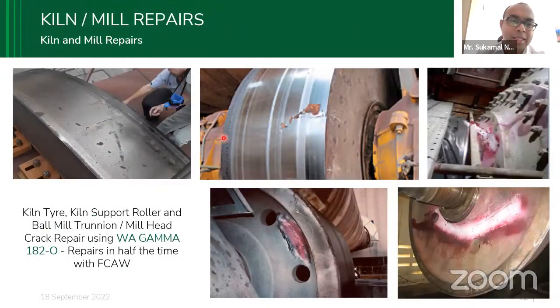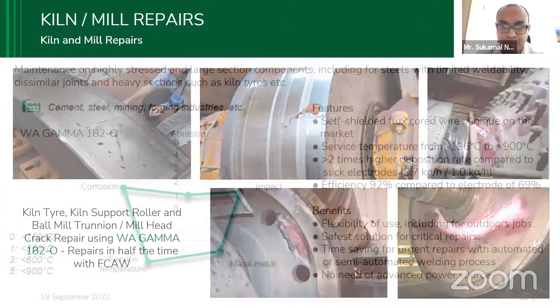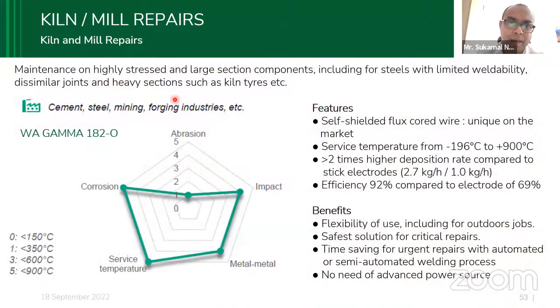So kiln and mill repair is basically, you can see this is a kiln tyre where it is very prominent how much crack or wear occurred. These kinds of components are very sensitive to cracking, and it's very difficult to repair. So we have the know-how to repair this one, and we use what's called Gamma 182, which is basically a nickel-based wire. So here, as I told you, that is how we determine what kind of consumables we need to use and what things we need to take care of.